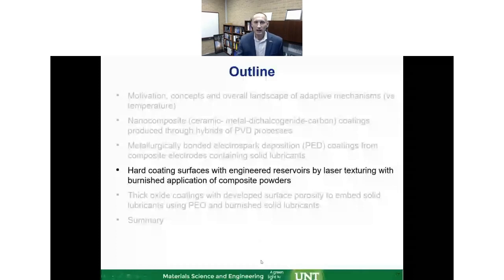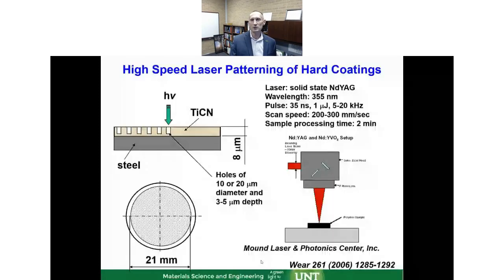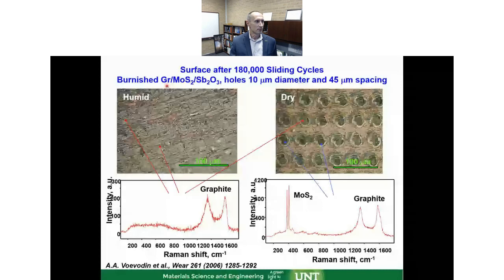Another example I want to highlight is, can we use some other methods? Laser texturing is another popular method where you can modify the surface to give it a different morphology, and we can use it to create reservoirs for solid lubricants. It's very simple. You take any hard coating, in this case titanium carbonitride, and then you do laser drilling with a high-speed motion stage and a pulsed laser, and in a matter of a few minutes you can engineer something like this. We have a bunch of dimples created on the surface, which will serve as reservoirs, and you can control the diameter and the depth of these dimples.